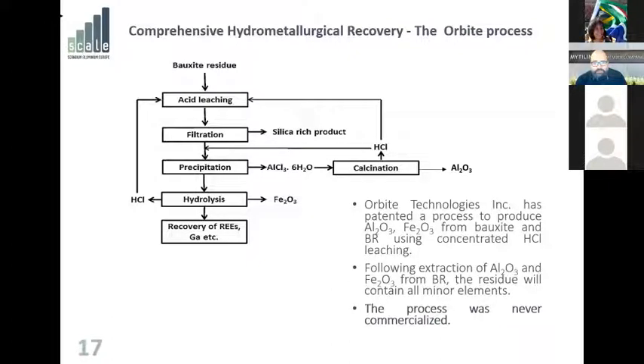By injecting hydrochloric gas into the solution, you are able to saturate out the alumina as aluminum chloride, and then you can calcine the aluminum chloride into aluminum oxide. Returning to your raffinate, you can do a hydrolysis to recover the iron, and then you are left with a solution that would contain the rare earths, the gallium, scandium, and all the other elements that were dissolved in the process. As I said, this process was never fully commercialized.